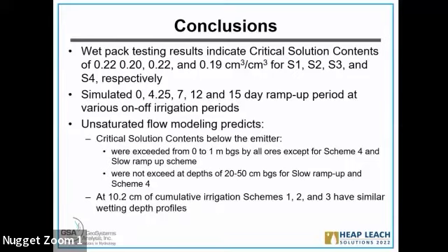What we found is that the slow scheme and scheme 4 can protect the ore from collapse at shallow depths. They collapse at the shallow structure between 20 and 50 centimeters, but from that point on, all the ore will not collapse. They only experience the shallow collapse, but from that point on, they are very smooth.